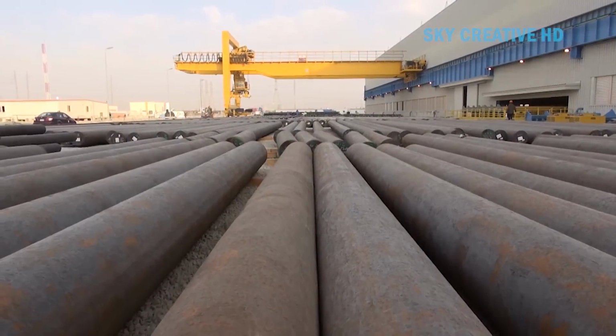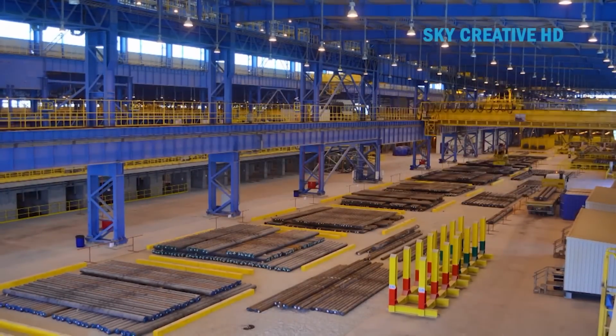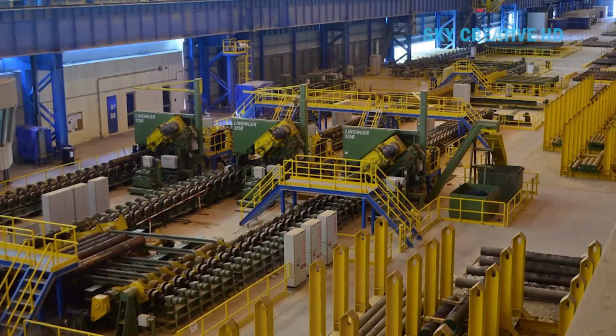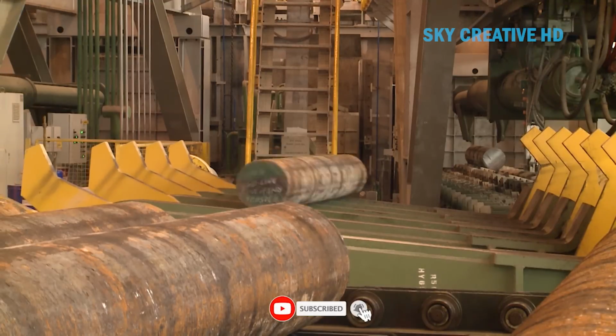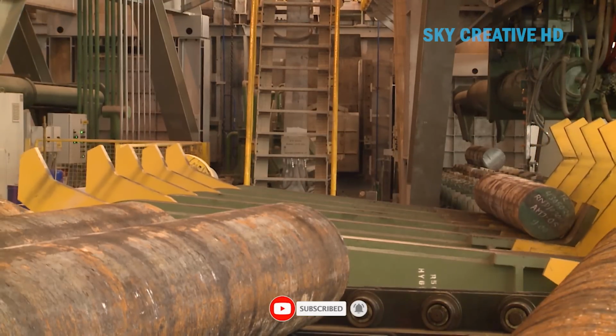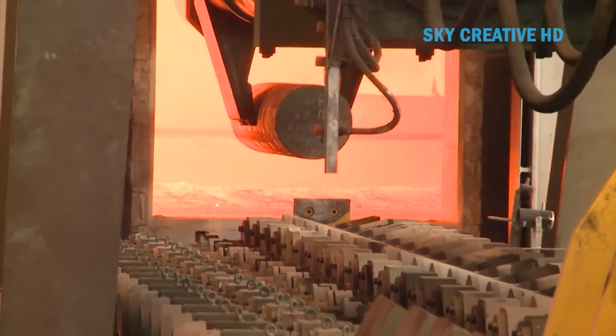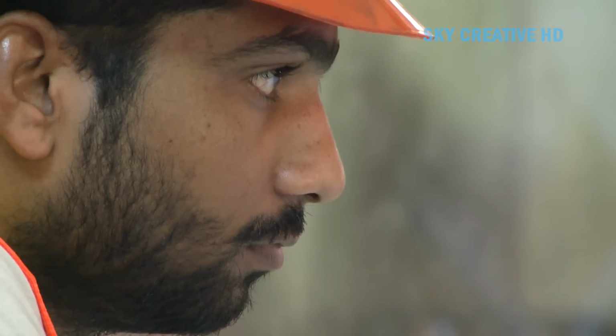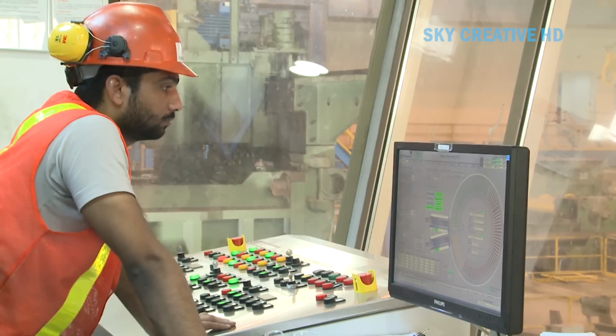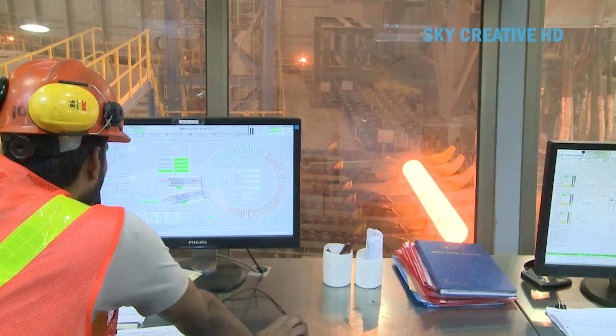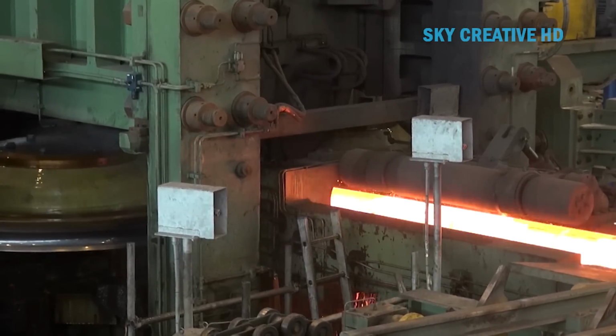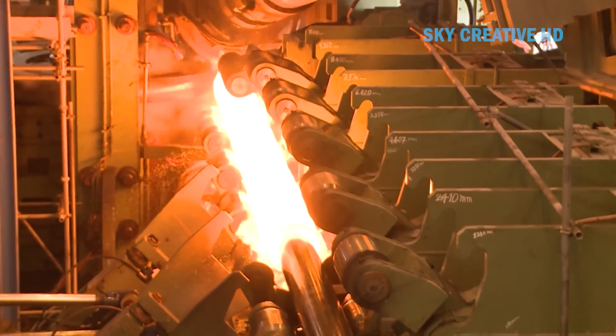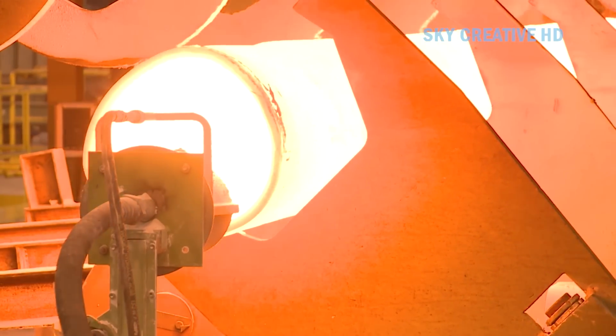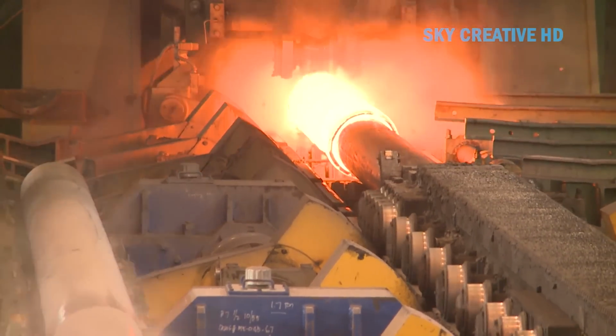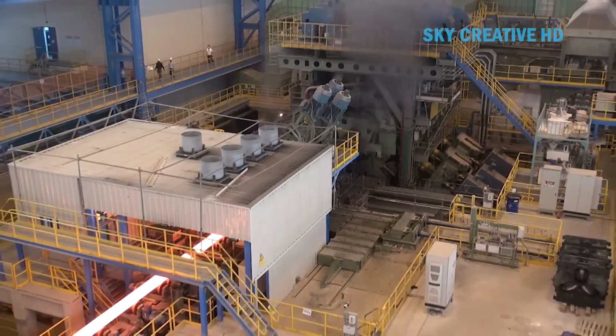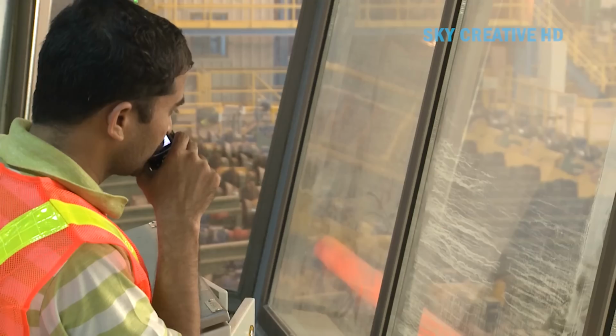ArcelorMittal's Jubail facility is a prime example of modern seamless pipe production, designed to meet the demanding requirements of the oil and gas industry. The process begins with high-quality steel billets, which are heated in a rotary hearth furnace. This furnace ensures uniform heating, crucial for the subsequent piercing operation. The heated billet is then fed into a rotary piercer, where a mandrel is forced through its center, creating a hollow shell. This piercing process relies on heavy-duty rollers and a precisely controlled mandrel to achieve the desired wall thickness and diameter. The rotary piercer's design minimizes stress on the material, ensuring a high-quality initial hollow.